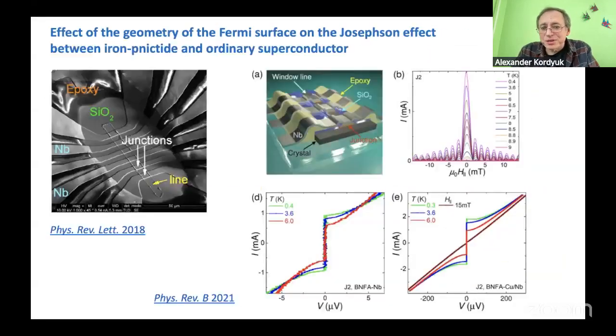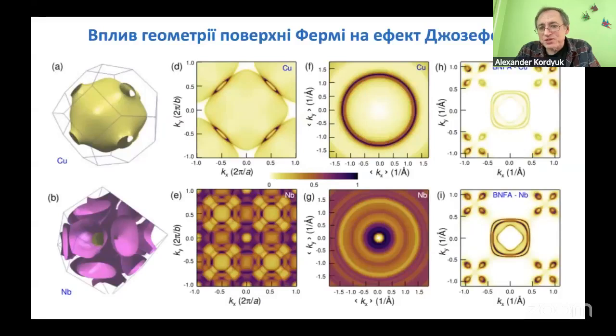But then we found an interesting thing: if we put a thin layer of copper in between niobium and the iron-based superconductor, this value increases 40 times. A 40 times increase was unbelievable, because we expected that copper, which is not a superconductor, would reduce this value, but it increased, and we understood why. Because the Fermi surface of copper, when integrated, is simple, and it looks like a circle. And this Fermi surface just looks like a filter in reciprocal space.